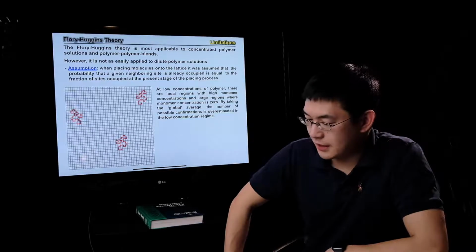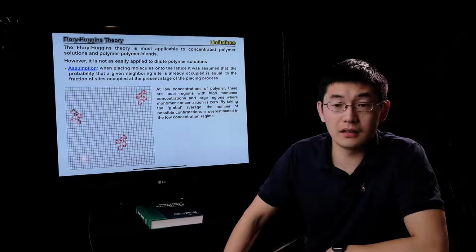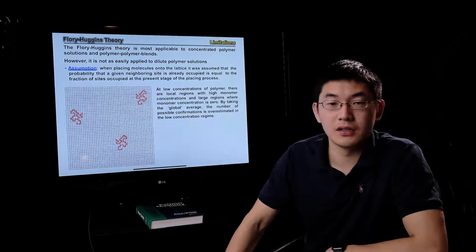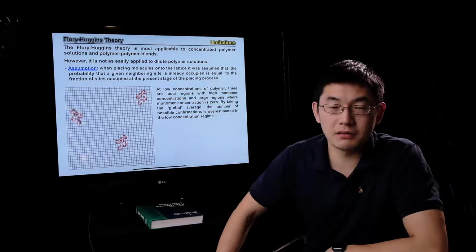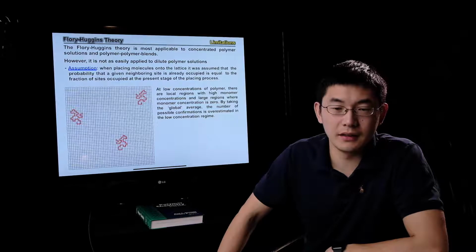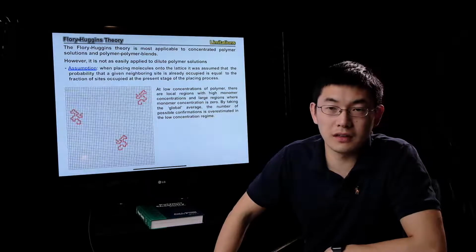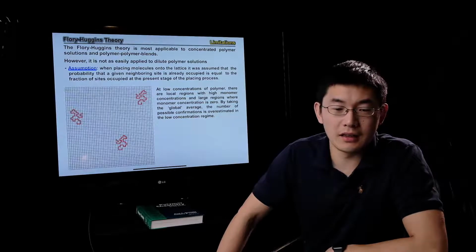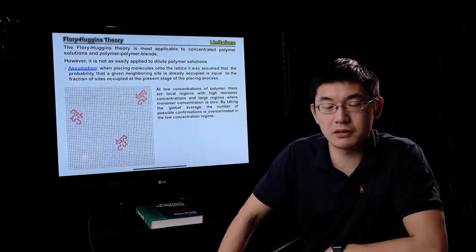Kundu, you are right about that. First, let's clarify one thing. A and B are constants, and they are not necessarily widely reported in many textbooks. Because it's very material system specific and combination specific, you should be able to find in published literature where, for example, toluene and polystyrene will give you a combination of A and B. And these are going to be constants specific to this material system.